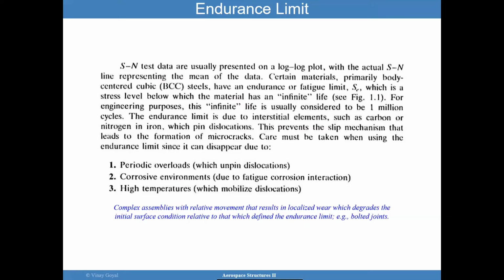The endurance limit is due to the interstitial elements, such as carbon or nitrogen in iron, which pin dislocations. This prevents a slip mechanism that leads to the formation of microcracks. But it is important to understand that this endurance limit can quickly disappear. If you have overloads, it will unpin these dislocations. If you have corrosive environments, this endurance limit is gone. High temperatures will make it easier to mobilize these dislocations. So you could have a situation where you thought you had an endurance limit, but that endurance limit is gone.